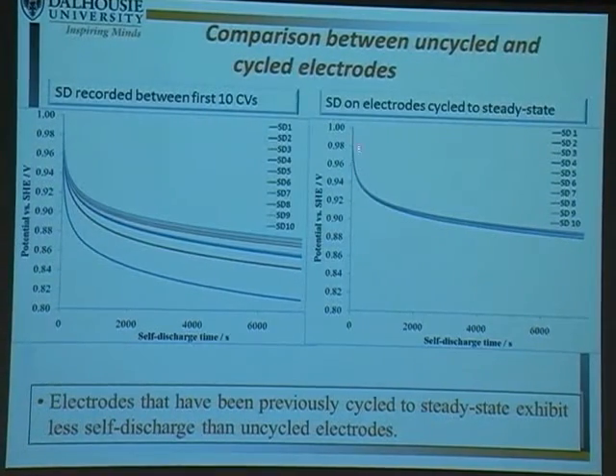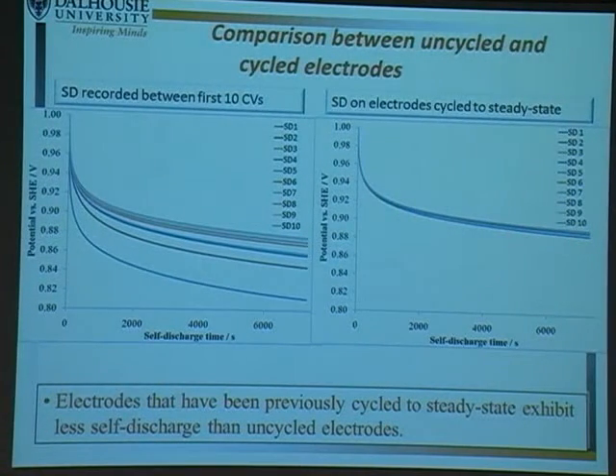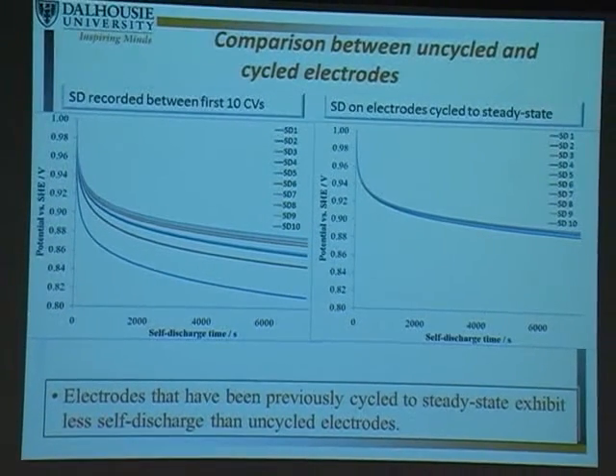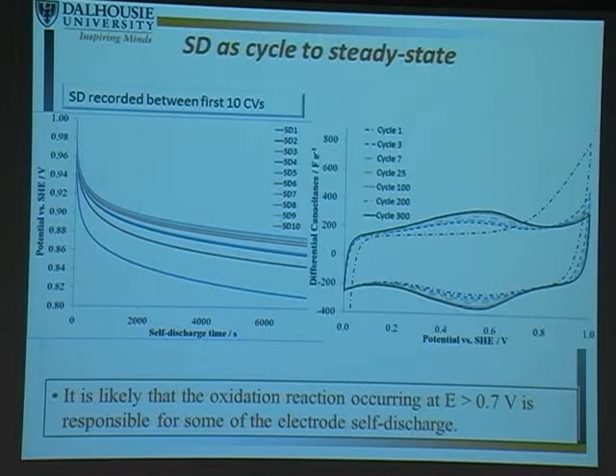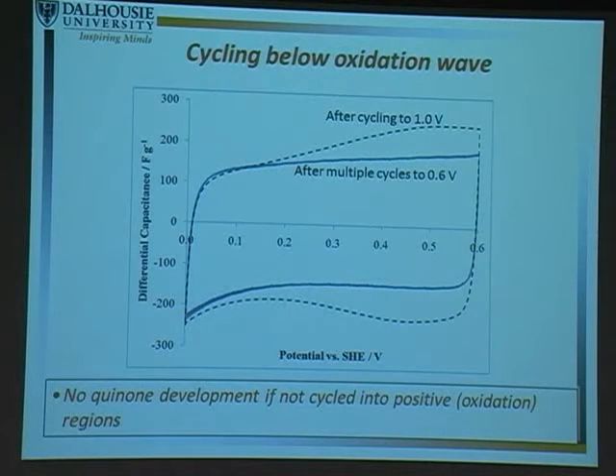For comparison, this is the self-discharge profile for an electrode that's been cycled to steady state. So that's where that oxidation wave has completely disappeared and those quinone peaks are developed. So we expect this self-discharge to be quite consistent. And again, what this suggested to us is that possibly this reaction right here is causing self-discharge. And so we put a lot of effort into trying to identify what that reaction is.